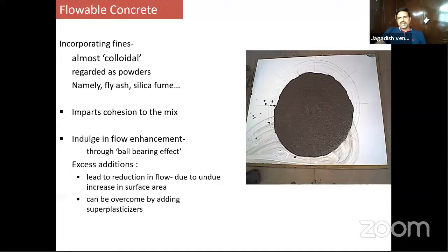So you need a flowable concrete to place in the congested reinforcement. At the same time, it has to flow. So how do you achieve flowable concrete without segregation or bleeding? By adding more fines. You cannot use more cement, so you cannot use beyond 450 kg of cement, because you need more powder to flow the mix. By incorporating fines, you can impart cohesion in the mix and you can enhance the ball bearing effect, that means the workability of the concrete.